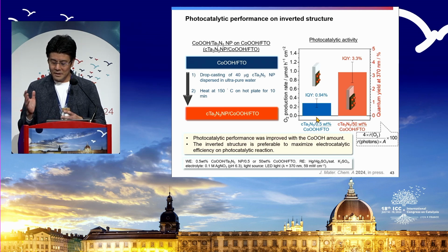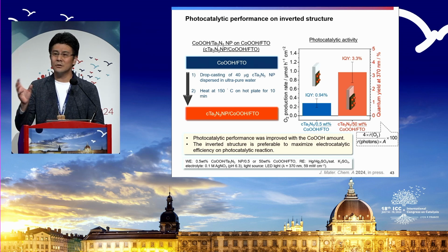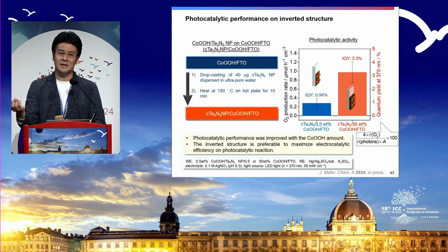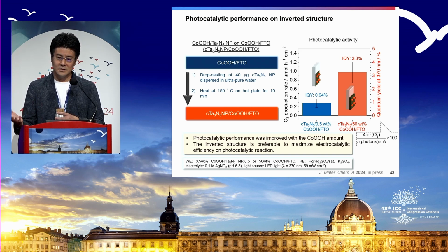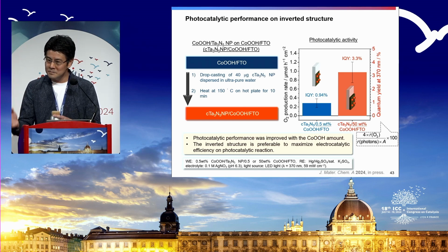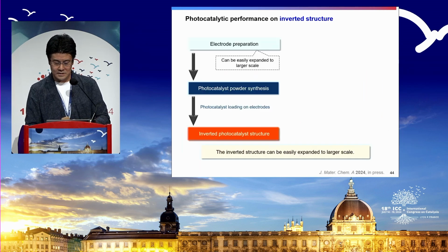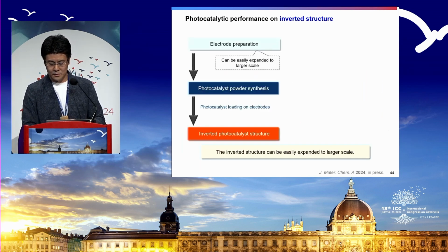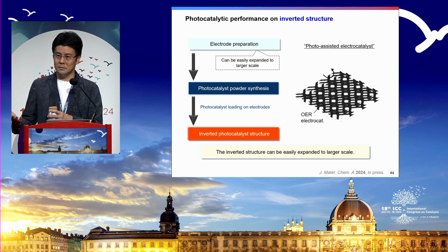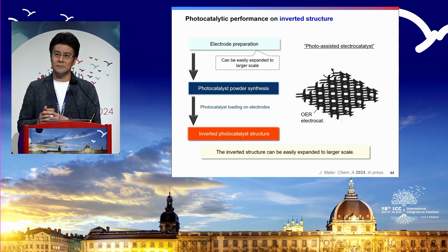So typically, what is missing for this visible light responsive material is not only the semiconductor materials. Yes, it's important that the carrier diffusion is very key. But an additional part is electrocatalyst. We don't have enough electrocatalyst material. So we need to come up with a combination of electrocatalyst. You need to put it but it becomes black. So how do you maximize this performance? In this paper, just accepted, this inverted structure was proposed. So make the electrode first. We make the powder photocatalyst material, and then we put them together. So the idea is, we already know how much performance you can get with this electrode. And you have to have a very good oxygen evolution performance.